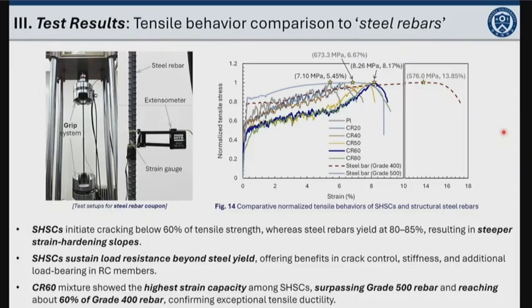The CR60 sample here showed the highest strain capacity among the strain hardening slag composites, surpassing grade 500 rebar and reaching about 60% of grade 400 steel rebar here, confirming its exceptional tensile ductility.